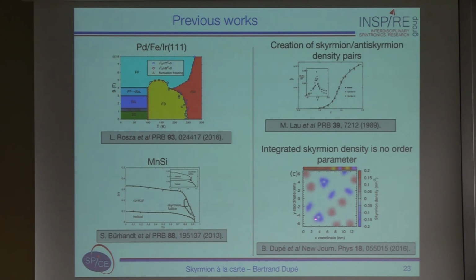And you see these triangular shapes here, which are higher order anti-skyrmions, and they have a very long lifetime, let's say, with the frustration of exchange interaction. If you calculate the topological charge of this supercell, you will get a topological charge of -1. So you would say that, okay, I should have 1 anti-skyrmion here, although you have a lot of different types of particles. So it suggests that the skyrmion number is not an order parameter.